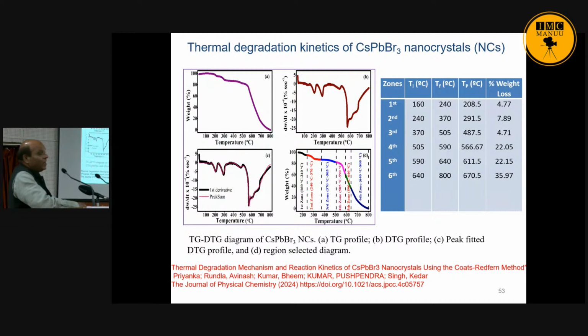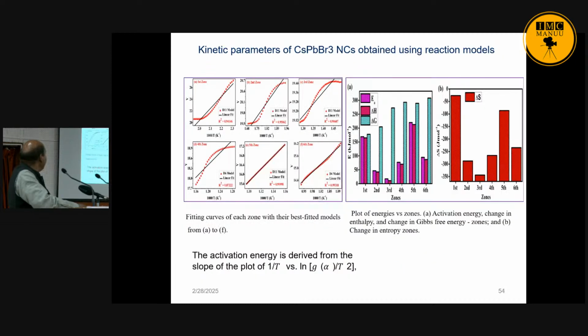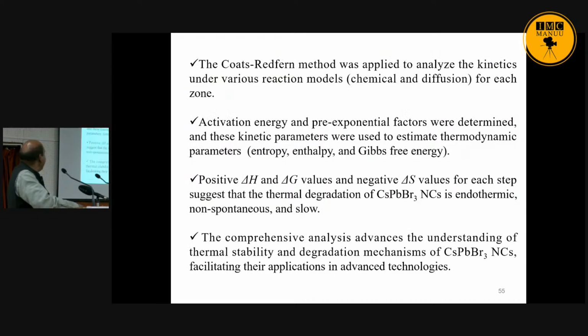Other work is on some thermal properties also. If you see the thermal property, there is some TGA. From TGA, we get different peaks, then we convert things here. Then we take the peak and obtain some kinetic parameters, and then we get the activation energy, Gibbs free energy, enthalpy and entropy. This is the change here. By the help of this, we understand the thermal stability and degradation mechanism of CsPbBr3, for application in advanced technology. Because we also know the thermal investigation of a material, so then we can use the material for devices.